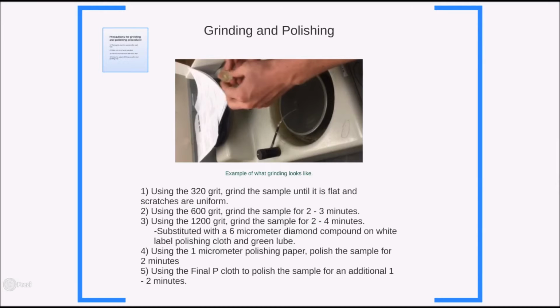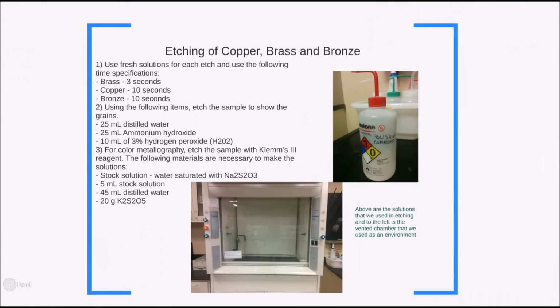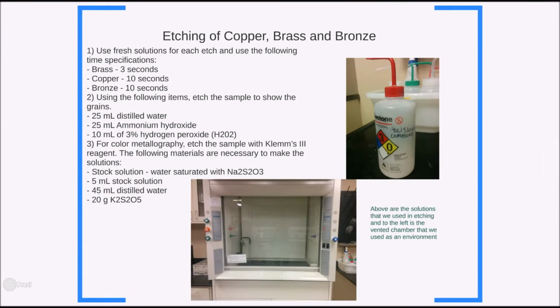Using the 1 micrometer polishing paper, polish the sample for 2 minutes using generous amounts of green lube. Using the P cloth with silica, polish the sample for an additional 1 to 2 minutes. Etching of copper, brass, and bronze. Use fresh solutions for each etch and use the following time specifications.